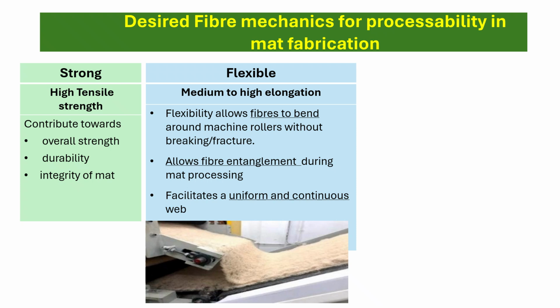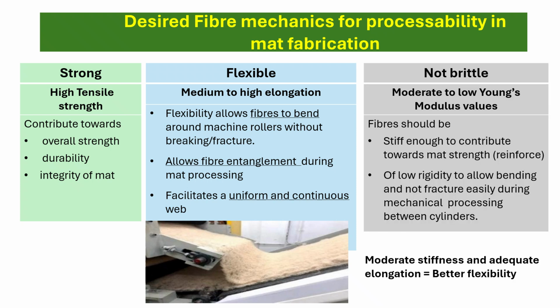Also, for a good mat to be produced, we need a proper networking of the fibers, and this is possible only when the fibers are flexible, so they can easily entangle between themselves, and produce a continuous and uniform mat. Also, we don't need fibers to be brittle, because brittle fibers will imply that they will be easily prone to break during the processing of the mat making. And also a mat made of stiff fibers would imply that the final product would be relatively weak.